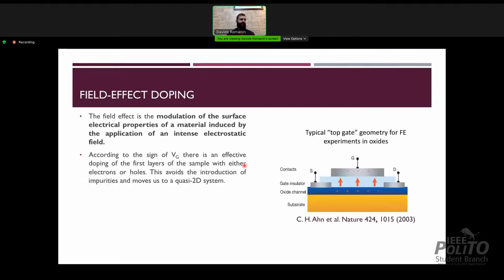Now, we are interested in finding a way to control correlated phases of matter without the inclusion of other chemical species inside our system. This can be achieved via field effect doping, which consists in the modulation of the conducting properties of a material by means of a transverse electric field, which can induce charges in the first few layers of a material. The experimental setup is that of a field effect transistor. We have a metallic gate through which we can tune an electric field via a gate voltage, a dielectric, and the system under study.